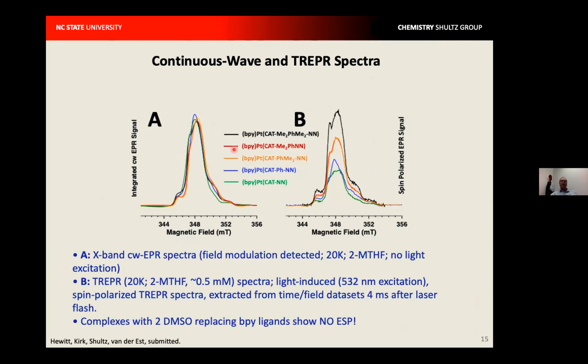So on the left are the integrated continuous wave EPR spectra of these complexes with no light irradiation. And on the right are the time-resolved EPR signals. And so these are effectively difference spectra before and after the light pulse. So we're only seeing EPR spectroscopy that is a consequence of spin polarization. And so what we see is when there's no molecular bridge, we get a relatively weak time-resolved EPR spectrum. And as we go up through the series and we cut off the interaction between the catecholate donor and the nitroxide acceptor, then in the excited state, we generate a relatively greater amount of spin polarization that is transmitted back down to the ground state.